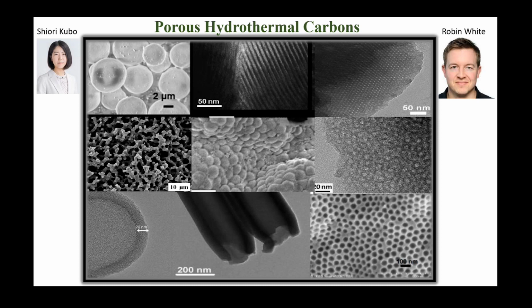And this is just to show that indeed, through using different soft, hard templating or in general material chemistry tricks, you can really nanostructure these carbons to pretty much any morphology you want, from spheres to ordered pores to spherical pores, macropores, mesopores, hollow spheres, or even hollow tubes. And so this is very nice because you could already pre-tailor your morphology depending on which applications you would like, and I'll show you some examples.